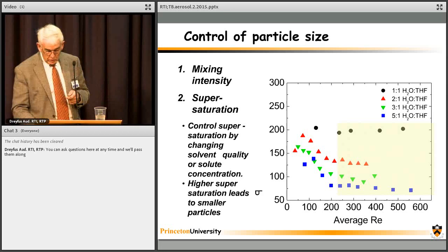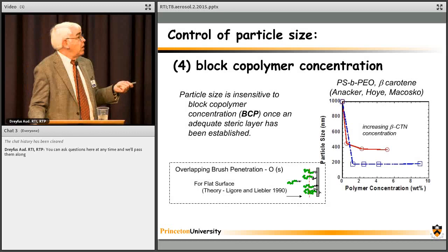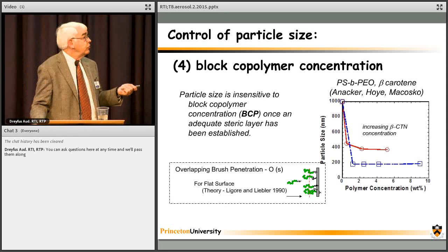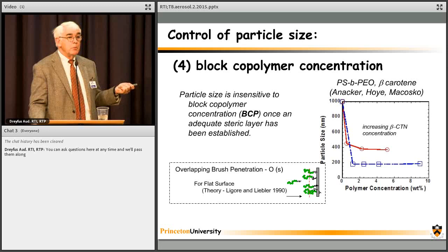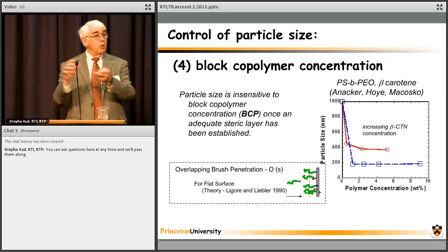Well, the polymer makes a difference, but it's a relatively modest difference. So this is particle size, and this is the concentration of polymer, and these are for two different supersaturations, actually. If we have enough polymer, then adding more polymer doesn't make things smaller. So it's not like a surfactant dissolving in oil, where if I put more surfactant in, I'm going to get smaller and smaller particle sizes.